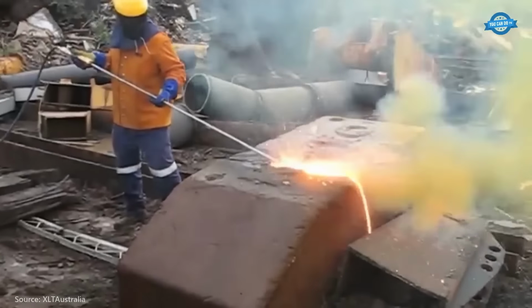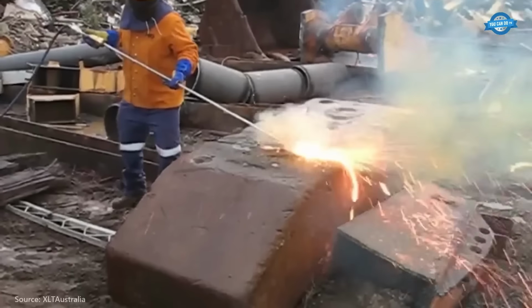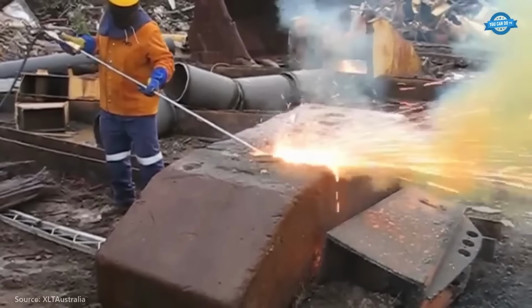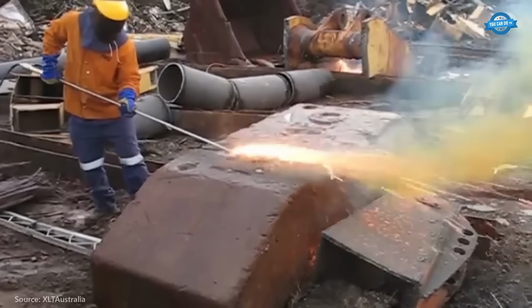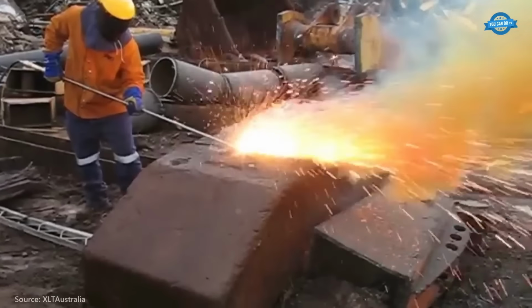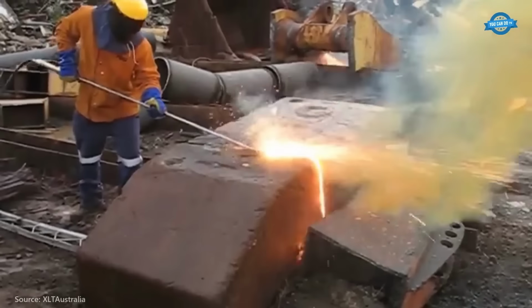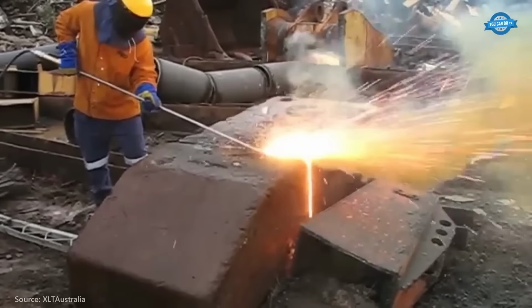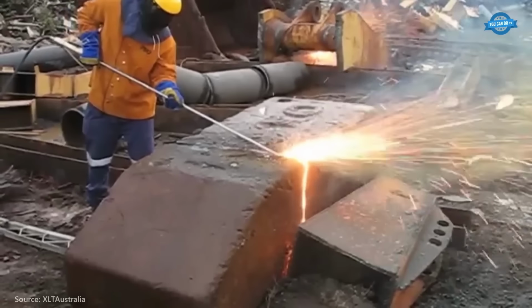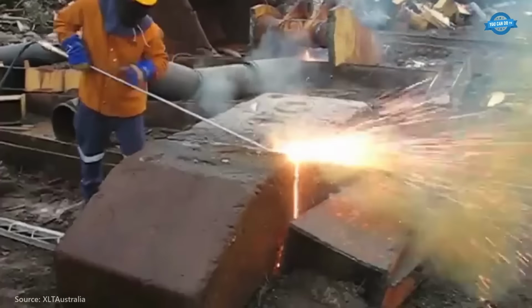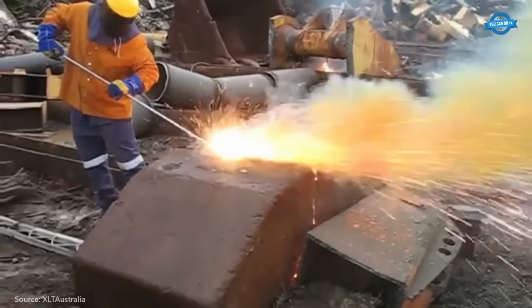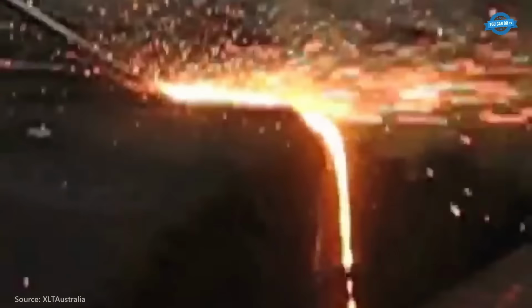The process begins with preheating the tip of the thermic lance using an oxyacetylene torch. Once sufficiently heated, oxygen is introduced, triggering an exothermic reaction that generates intense heat. As the operator moves the lance across the counterweight, the metal liquefies and oxidizes, forming slag that drips away, leaving a precise cut.